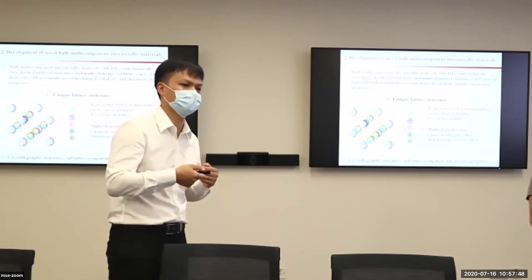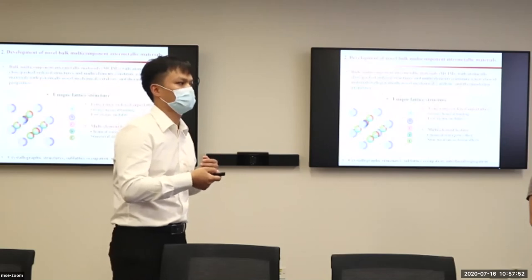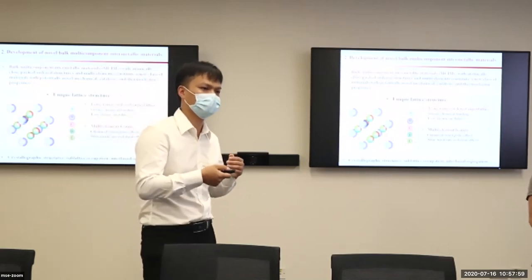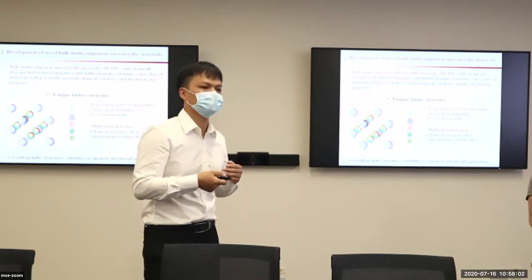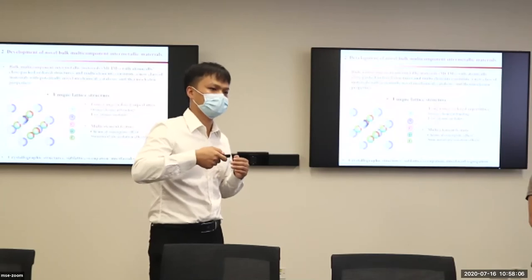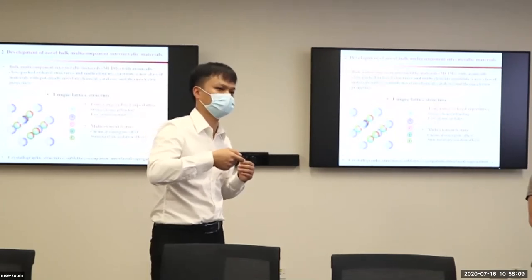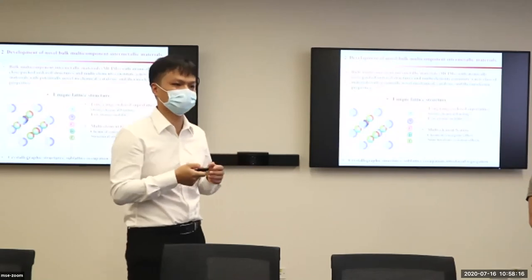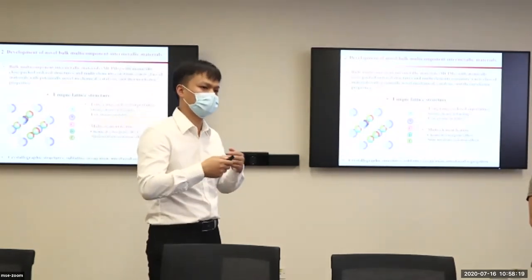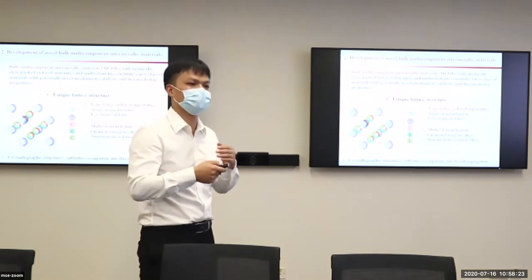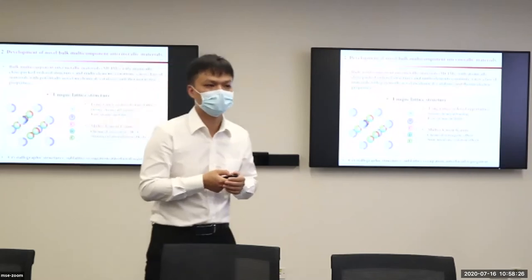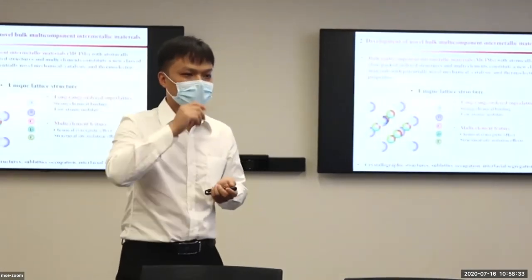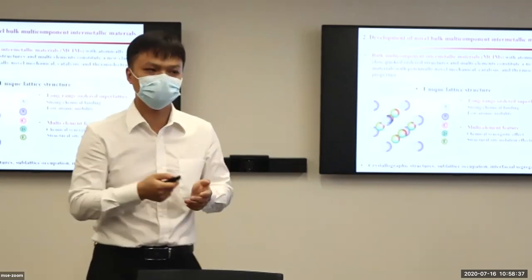especially the chemical reactivity. The first thing is that now we try to use vanadium, niobium, and molybdenum to introduce this site to cause lattice distortion. The second way is to insert interstitial atoms like carbon and boron into the lattice, to increase the lattice distortion and explore whether the change of the lattice structure will increase the reaction activities. Can you control the strain as well? We can control it. There are a lot of reports saying how different strain of the material changes the catalytic activities. Yes, now we can control it very well.